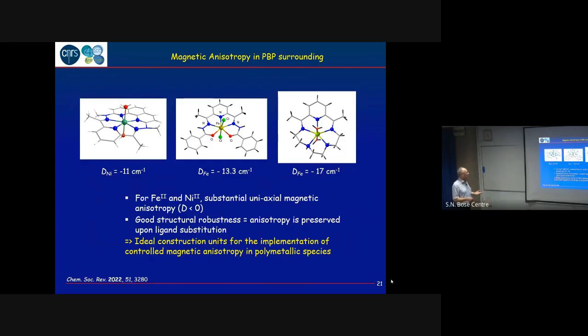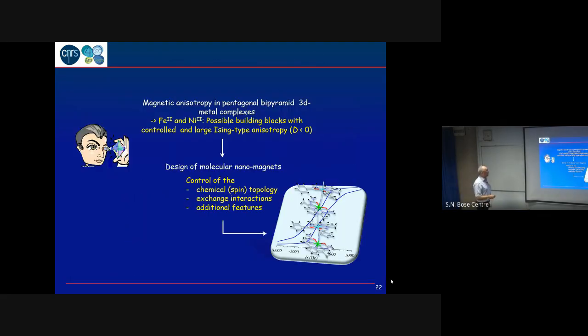So to us, what was interesting is, of course, the iron and the nickel complexes for which we have large uniaxial magnetic anisotropy and a very good structural robustness. So you keep the properties you have in your starting material, and this is the ideal situation if you want to construct polynuclear systems controlling what you put in your system. So the next step here was to use these molecules as building blocks and try to make chain compounds, because this is our main interest. And when you do that, you need to implement some other aspects.